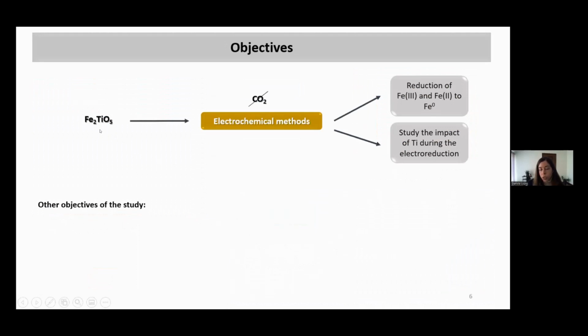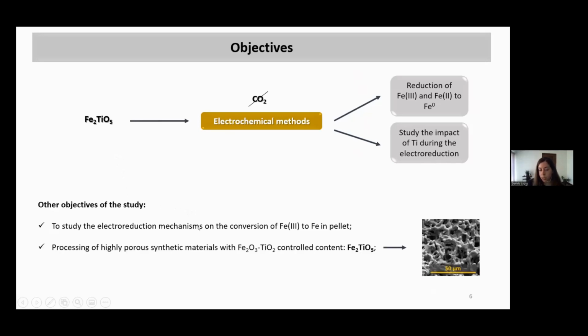So our goal is to reduce pseudobrookite in this electrochemical reduction in alkaline medium into metallic iron, and we also want to study the impact of titanium during the reduction. For this, we are going to study the conversion in bulk, in pellets, but it's not just simple pellets. We process highly porous cathodes to study this reduction to metallic iron, because it has easy access of electrolytes into the pellets, and also facilitates the escaping of hydrogen. After this, we also study the suspension mode, because it's more feasible for the pilot scale.